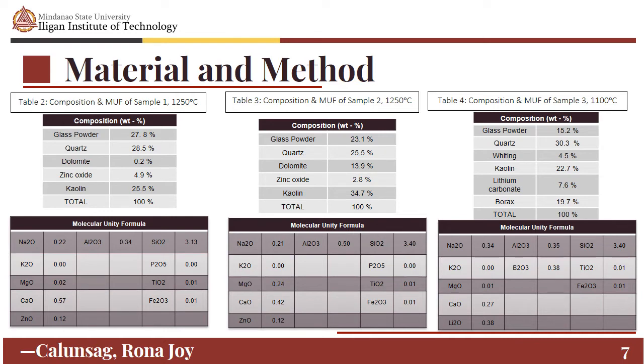So the table 2 shows the composition of sample 1 fired at 1250 degrees Celsius. So in the left side shows the composition by weight percentage, and for the right side shows the molecular unity formula. So for the composition, the glass powder has 27.8 percentage, and for the quartz, 28.5%. The dolomite has 0.2%. The zinc oxide has 4.9%, and the kaolin for 25.5%, a total of 100%.